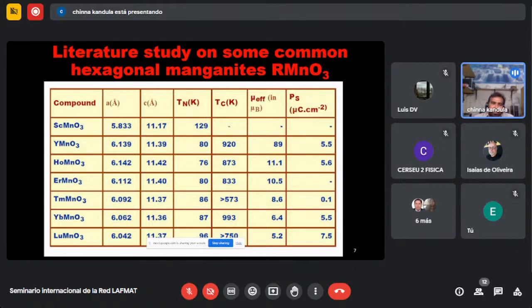In YbMnO3, the literature shows initial lattice constants like a equal to 6.0 angstroms and c like this. It shows a Néel temperature at around 87 Kelvin, and the effective magnetic moment is 6.4. Compared to that, lutetium manganese oxide gives 5.2. Lutetium is diamagnetic in nature, so the effective magnetic moment must be reduced. I want to check whether that happens or not.